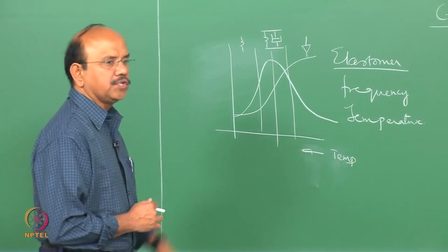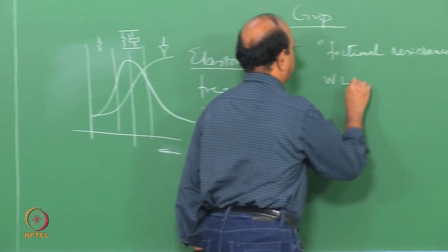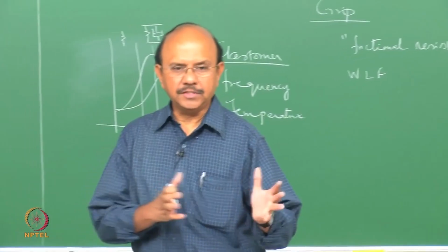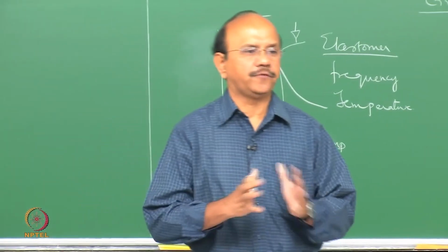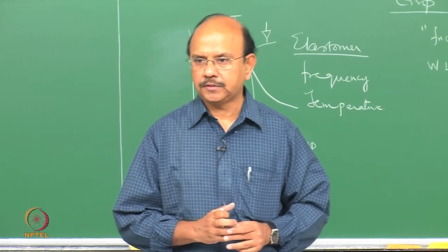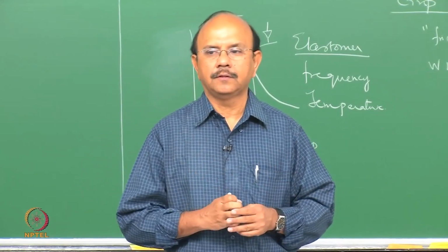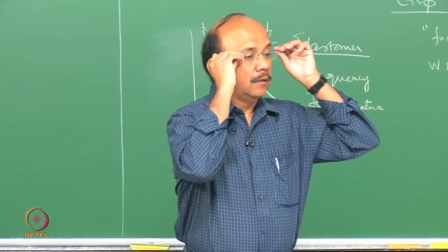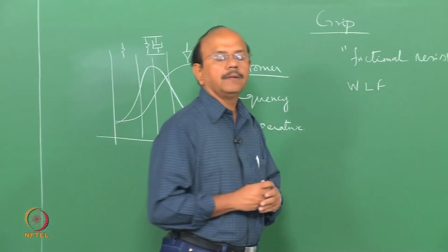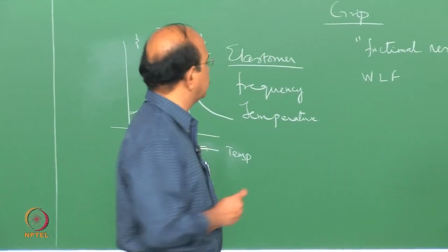We said that there's a relationship between the two, given by the Williams, Landel and Ferry WLF equation. This equation gives a shift in frequency when you shift the temperature. When there's a shift in temperature, you would see that there's a shift in frequency as well. We will come to that in a minute. Just summarizing what we said yesterday, in the last class.